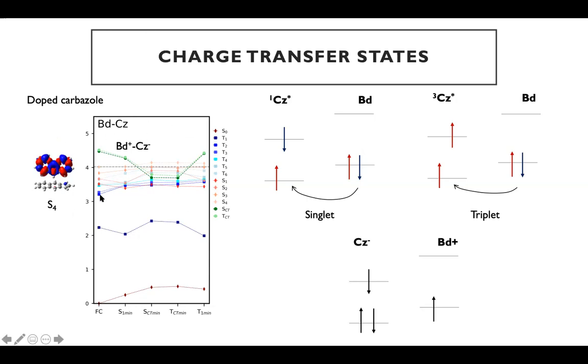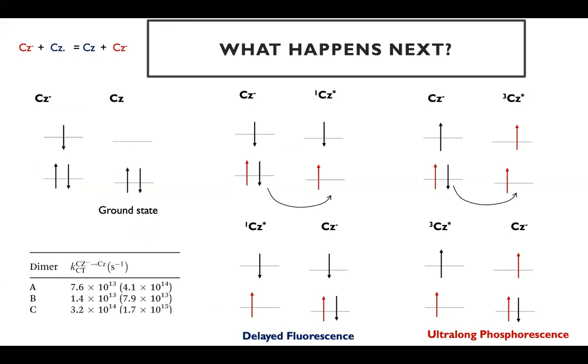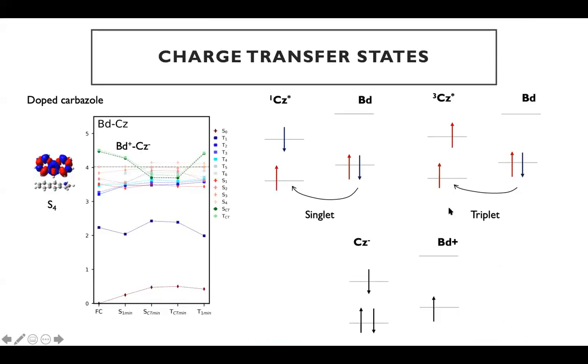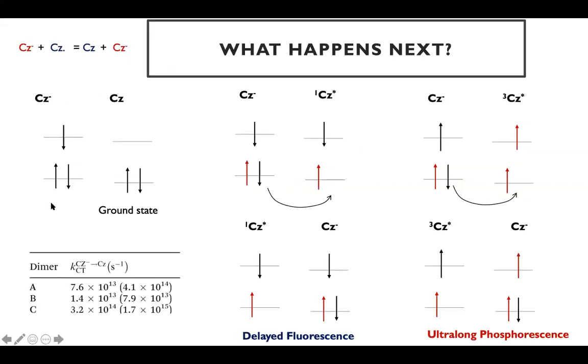And if we look at the electronic densities at the beginning of the process, you can see that the electronic density is localized on the carbazole molecule. And if you look at the charge transfer states, you will see the separation of charges when you have the interface. So what happens next? What's the next part of the process? Essentially, the charge is most likely trapped on the impurity, because of the alignment of the energy levels, there is no way of moving this positive charge, so it is going to get trapped on the impurity, and then the negative charge can transport through the crystal.